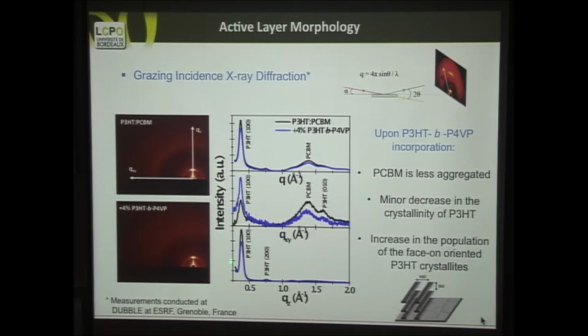And then by comparing these two diagrams here, this is by integrating the intensity on the plane here, the XY axis, in this direction. And we compare this to the integration of the intensity in this direction. What you see here is that in plane we have higher intensity for the one where we added the block copolymer, and out of plane we see it reducing. So what happens really here is that when the polythiophene is crystallizing, you have these rods that are like planes. They are crystallizing parallel to each other.